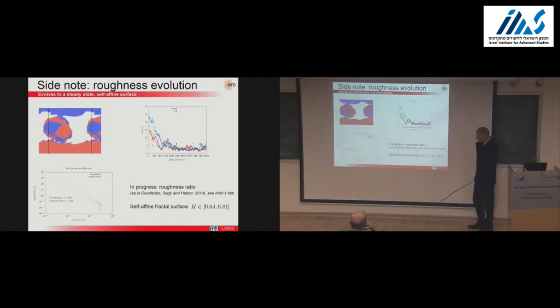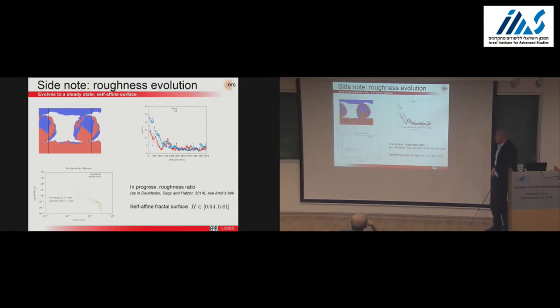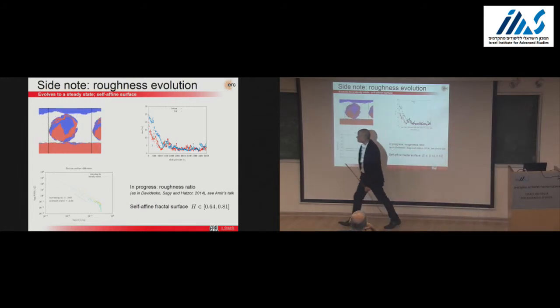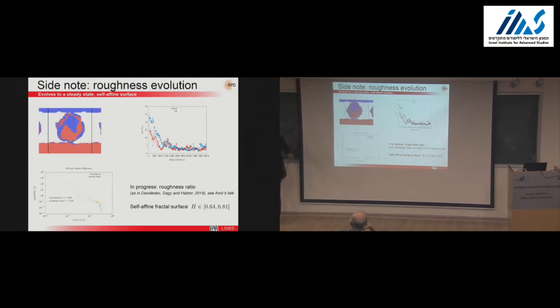And then I know there will be a talk by Amir this afternoon on surface roughness evolution in rocks. And this is not a very good plot here. But being here a physics committee in front of me, I have to say that we do observe scaling laws with some fractal behavior, H between 0.6 and 0.8, let's say. It's not a very good image, but we have only 2 decades, unfortunately, of scaling. Why only 2 decades? Well, because those are very expensive calculations. We have only a small surface. So we hope to go to 3D. We hope to enlarge the system size. But we really want to understand what sort of exponent is emerging from the type of material properties we put in our system.